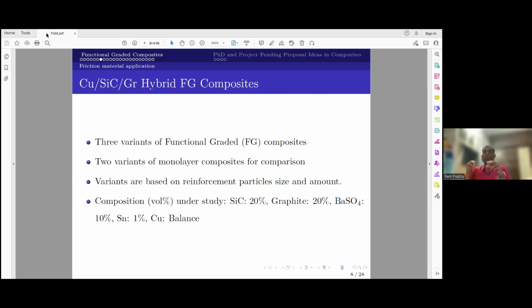Now I'm going to introduce the functional gradation. How am I going to do it? I'll show you in the next slide. We have developed 5 composites. 2 are my benchmark, the existing composites. 3 are the functionally graded composites. All of them have the composition I showed: silicon carbide, graphite, barium sulfate, tin, and copper. Tin is added to facilitate liquid phase sintering during my powder processing, called powder metallurgy. Graphite plays the role of friction stability because it's a lubricant. Silicon carbide strengthens the composites, improves the load distribution, and increases the hardness of the material.